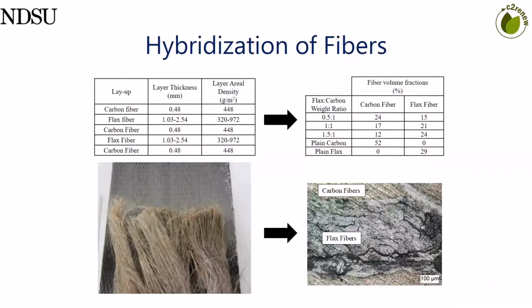I talked a little bit about hybridization and the opportunity to gain the best of both worlds. You can take a natural fiber such as flax or hemp and combine it with carbon fiber, which has very high strength and stiffness, and you gain the best of both worlds in terms of strength, stiffness, as well as reduction of your standard deviation of properties. That comes out of the carbon fiber. What you gain out of the natural fiber are things like vibration dampening, higher specific strength and specific modulus, as well as sustainability in terms of utilizing a natural material and less of the synthetically produced reinforcement.